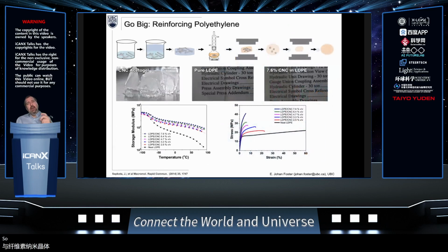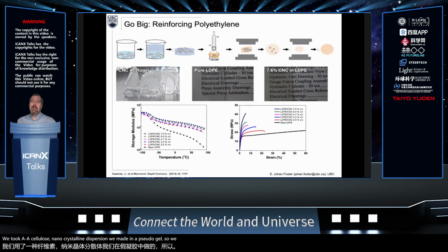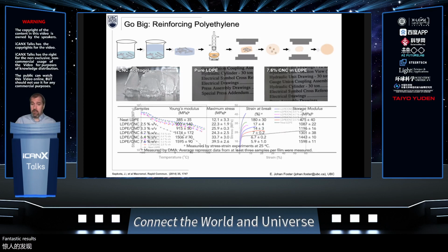Years ago, we tried to do this with our solvent methods. We took a cellulose nanocrystal dispersion and made an aerogel, no, an aceto gel, so we replaced the water with acetone. That's a nice gel-like material on the left. We imbibed in our polyethylene, so we dissolved our polyethylene and put that inside and pressed it. Fantastic results, which I'll show here.